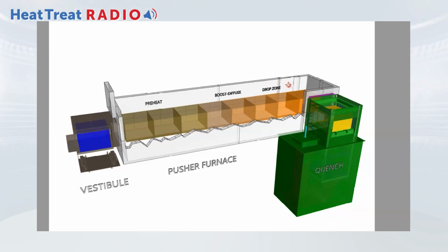And if the components that we're heat treating are distortion critical, it's very important as to what the temperature is prior to quenching. So we carburize at a high temperature, 1700 Fahrenheit, 1750 Fahrenheit, because the diffusion rate is much higher at that temperature. But we only want to quench these parts at 1500 or 1550 because we want to have an absolute minimum amount of distortion.